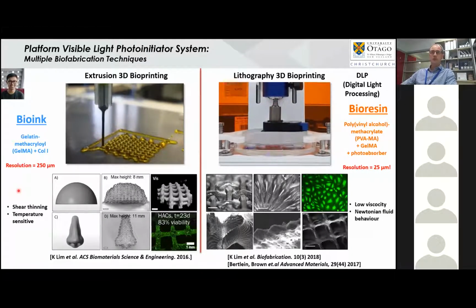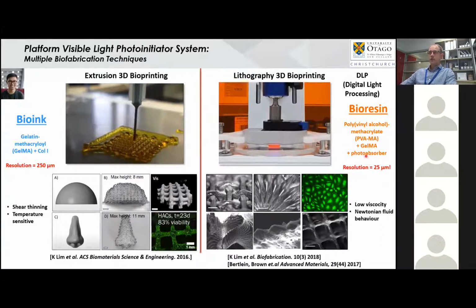Here's some examples where we've used the photoinitiator system to then create bioinks for extrusion bioprinting, including obviously gelatin methacryloyl, where we can then get quite large constructs with quite high shape fidelity, maintenance of shape fidelity, and cell viability. We were obviously very keen to try and see if we could use it for different lithography-based bioprinting.